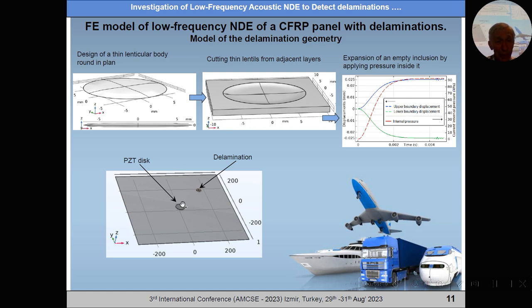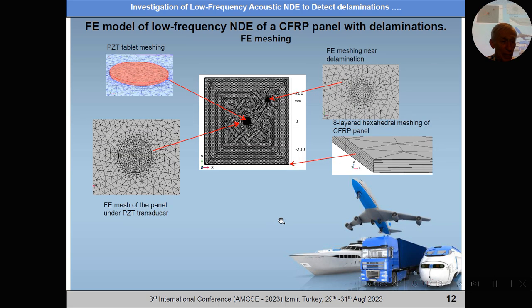The piezoelectric disc was installed at the center, and the delamination was placed on the diagonal of the square at a distance of 23 cm from the center. To correctly describe the wave propagation process near the exciter and the delamination, the finite element mesh was significantly refined. It should be noted that in works modeling acoustic diagnostics of delamination, their geometry is typically presented as a thin rectangular prism, which facilitates solution of the problem, but in practice, laminations always have a lenticular-like form.